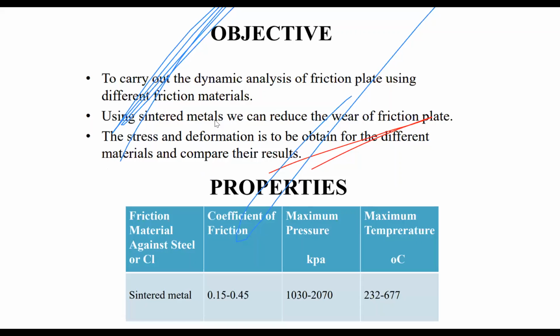So the objective here is to carry out the dynamic analysis of a friction plate using different friction materials. So we're going to use the sintered metal where we can reduce the wear of the friction plate, and then the deformation. These are the values that we are going to get for the friction material. It is being used against a steel or a cast iron. And here the coefficient of friction is between 0.15 to 0.45, and the maximum pressure is 1030 to 2070, and the maximum temperature can go up to 677 degrees Celsius.